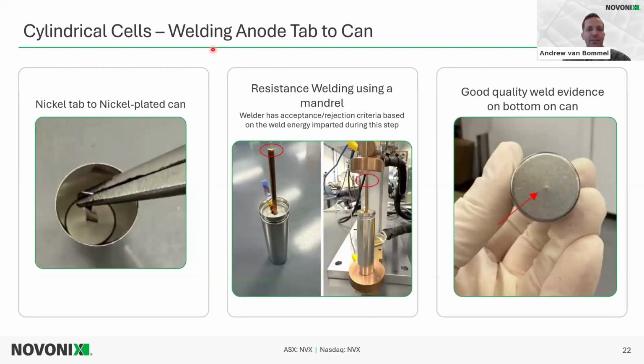For welding the anode tab, this is just some pliers holding a nickel tab. This is not how it's welded. It's just showing the nickel tab placed on the bottom of the nickel-plated can. In reality, the nickel tab is in the bottom of the jelly roll, and to be welded, the jelly roll is inserted. So that nickel tab will be on the bottom of the jelly roll, and a mandrel is placed, and then that tab will be resistance welded.